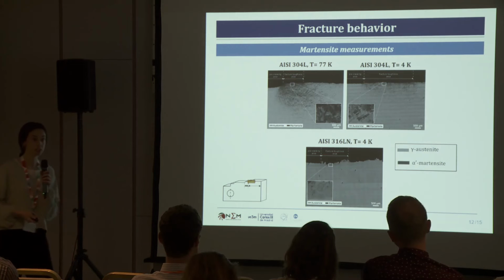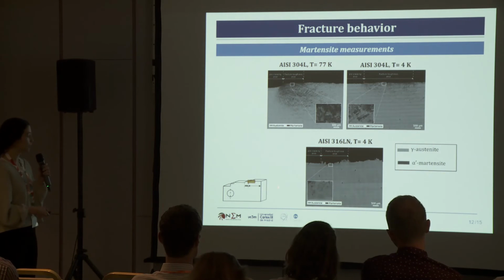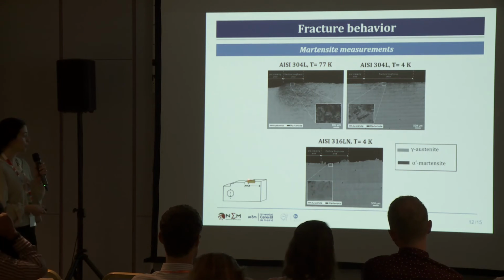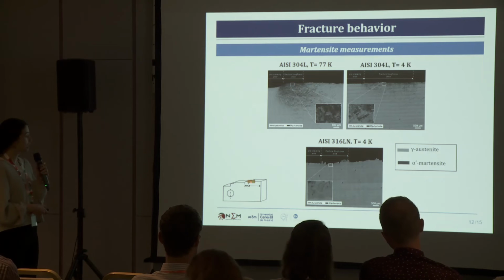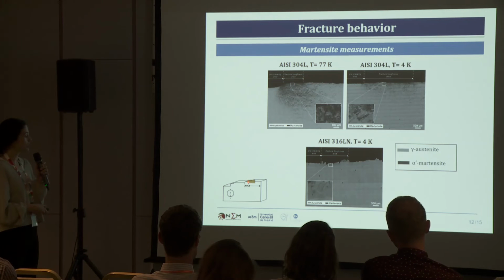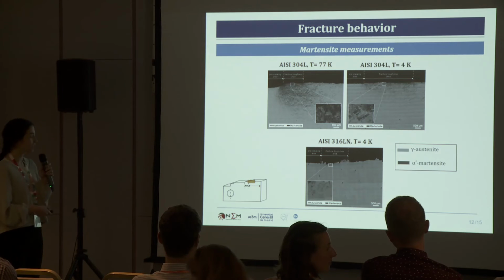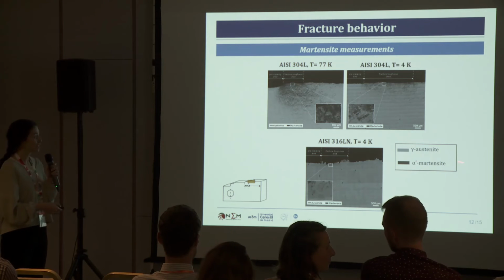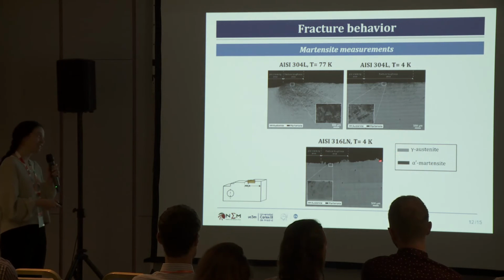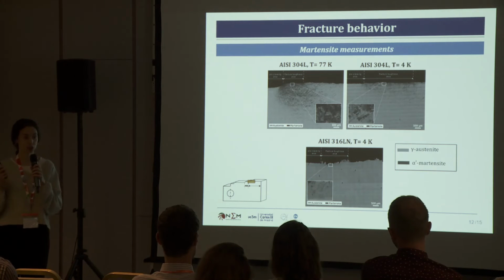So what we are seeing here is, after the test, we have half of our specimen, and we do a micrograph stitching on this area. You cannot read anything, but you can see part of the pre-cracking area and then part of the fracture toughness area. You see in dark the martensite and in light the austenite. For all of them, we see that the higher content of martensite is in the fracture surface. Why? Because it's where we have the higher deformation.